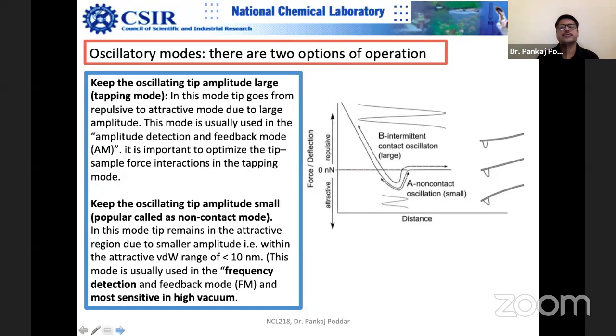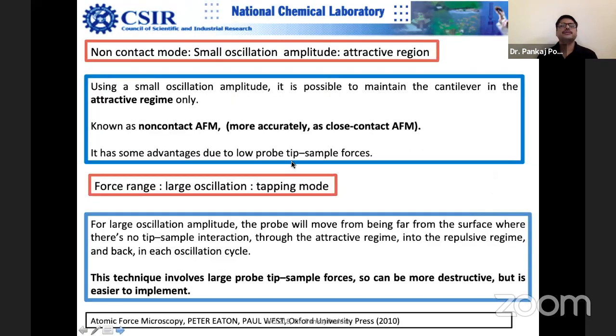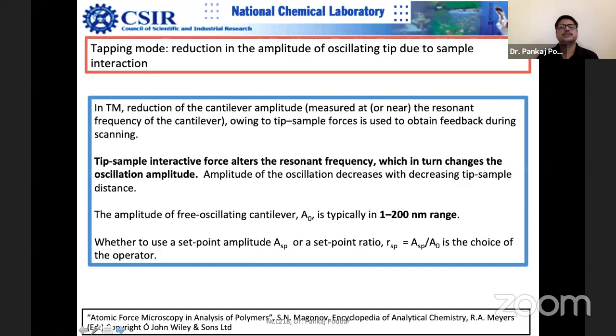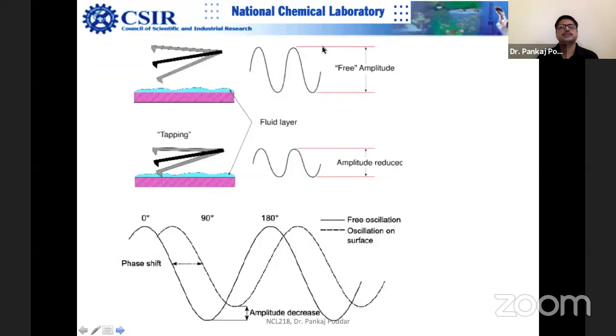So let us look at the tapping mode. As I mentioned, the non-contact mode is basically small oscillation amplitude in the attractive region, and this is more accurate, and it is close contact. Tapping mode is basically large oscillations. This technique involves large probe-tip sample forces, so it can be slightly destructive also, but not that much. So let me move on. As I mentioned, in the dynamic mode, this is the free amplitude.